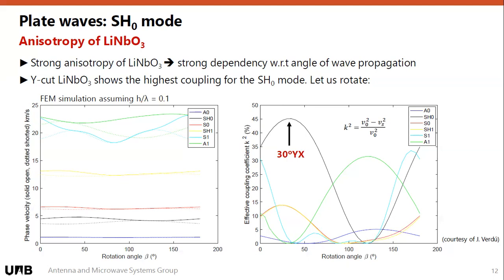You can see that here there are a lot of other modes, because all of them can exist on your plate. So you have your asymmetric and symmetric modes and their higher order harmonics. So you have S1, A1, SH1, and you have the coupling of all of them here. What is really good here is that when you have a lot of coupling to your SH0 mode, you have super weak coupling to the rest of the modes, excepting the symmetric mode. We will see that the symmetric mode is actually popping up as a spurious in our measurements, but it's really contained, because we will see something now on the next slide.